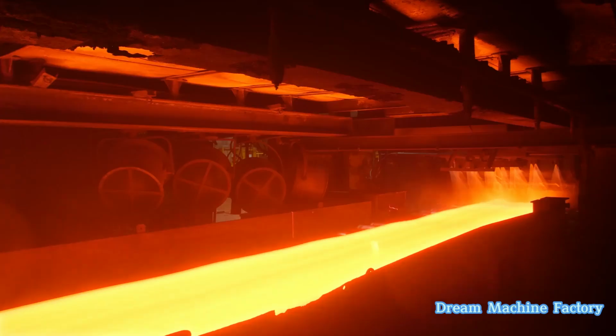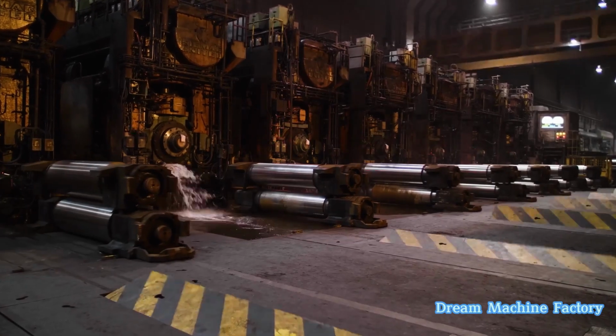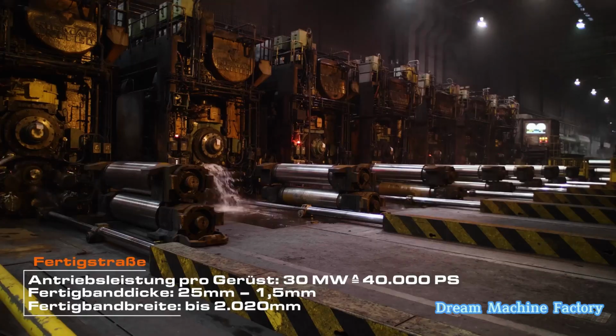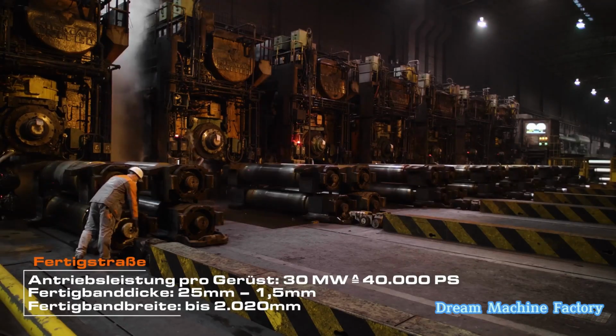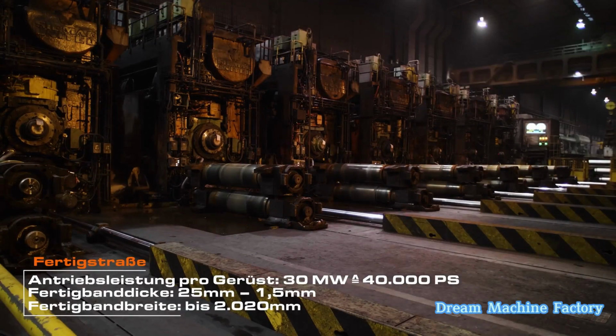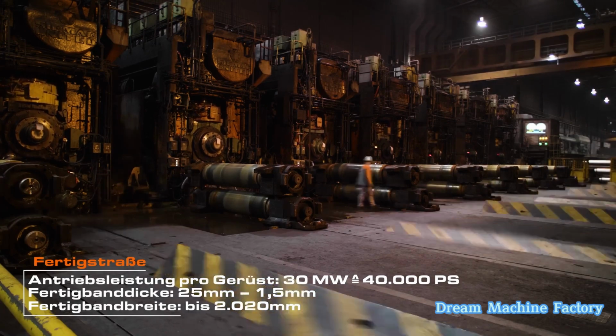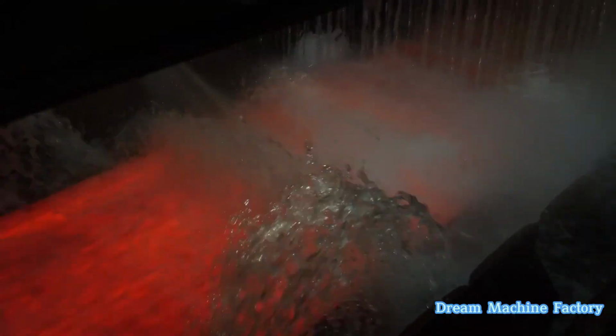In the final rolling stages, high-powered stands with a drive capacity of 30 megawatts, about 40,000 horsepower per stand, further refine the thickness and width of the steel strips. The final product can have a thickness ranging from 25 millimeters down to 1.5 millimeters and a width of up